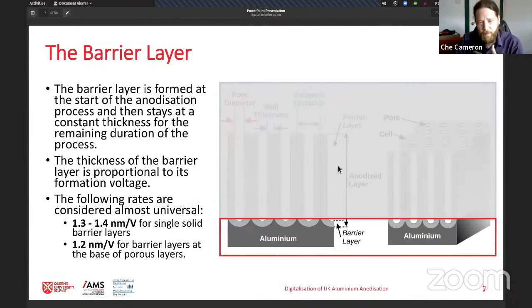So we'll start by talking about the barrier layer, which is the simple solid layer that forms at the surface of the aluminium. So you have bare aluminium metal and then an oxide layer formed on top of that. And this is formed at the start of the anodization process, and it will remain at a constant thickness as you keep running the process. This is a well-established mature process, and there are universal rules for how thick that layer will form based on the voltage you apply to the circuit.